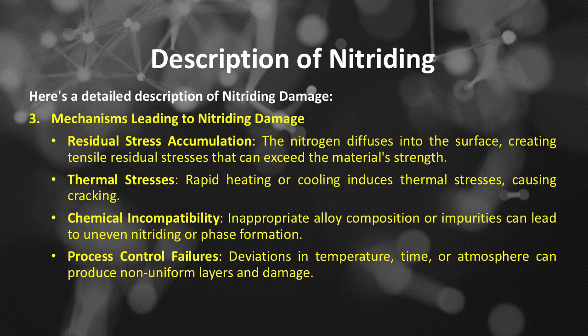Number 3 of the detailed description of nitriding damage is mechanisms leading to nitriding damage, which includes: residual stress accumulation, where nitrogen diffuses into the surface, creating tensile residual stresses that can exceed the material's strength; thermal stresses, where rapid heating or cooling induces thermal stresses, causing cracking; chemical incompatibility, where inappropriate alloy composition or impurities can lead to uneven nitriding or phase formation; and process control failures. Deviations in temperature, time, or atmosphere can produce non-uniform layers and damage.